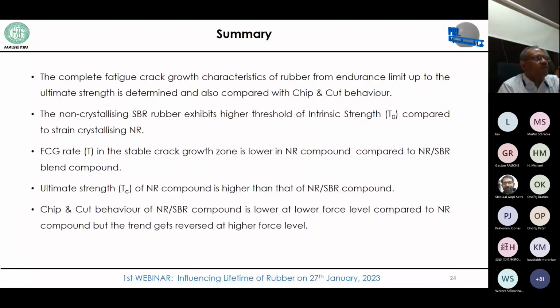So in summary, the complete fatigue crack growth characteristics of rubber from endurance limit up to the ultimate strength is determined for these two compounds. Non-crystallizing SBR exhibited higher threshold of intrinsic strength compared to the strain crystallizing NR, and FCG rate in the stable crack growth zone is lower in NR compound compared to the NR SBR compound. Ultimate strength of NR compound is higher than that of NR SBR compound. Chip and cut behavior of NR SBR compound is lower at low force level compared to NR compound, but the trend gets reversed at higher force level. So that is the key while you use it for a practical application.